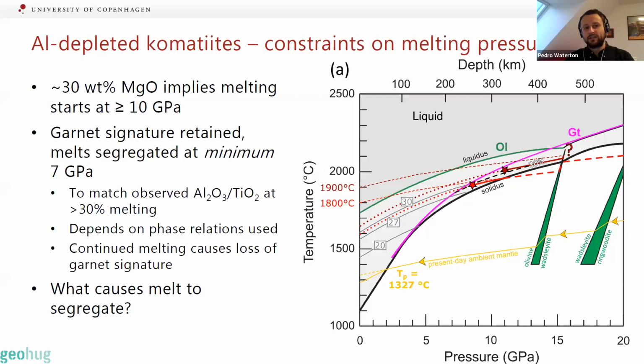I'll start with aluminium depleted komatiites because these have the best constraints on the melting pressure. So again, moving back to this idea of the MgO content of near solidus melts, aluminium depleted komatiites have about 30% MgO. And this implies that the melting starts at very high pressures, greater than or equal to 10 gigapascals, which is about 300 kilometers. Now, because we're retaining a garnet signature in the melts, we need to segregate the melts before we hit the garnet out curve, and also after we reach about 30% melting. And this depends a lot on what phase relations you use, but this means that essentially the melts have to segregate at a minimum of 7 gigapascals or a couple of hundred kilometers.